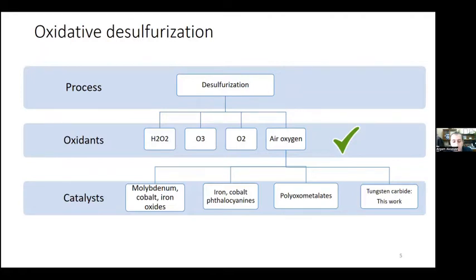The number of works in the field of oxidative desulfurization has recently increased significantly. It should be noted that in most works, environmentally friendly hydrogen peroxide is used as oxidizing agent. But an increase in total sulfur content in the feed requires significant volumes of this oxidant, which increases the cost of such crude purification and complicates the practical implementation of this approach. Therefore, using air oxygen as oxidant appears to be the most viable approach. The key issue for the use of air as an oxidative desulfurization agent is finding a catalyst that would allow the selective oxidation of sulfur-containing compounds in a hydrocarbon environment. One of the key disadvantages of known catalysts are difficult synthesis procedures which negatively affect the cost of such purification.